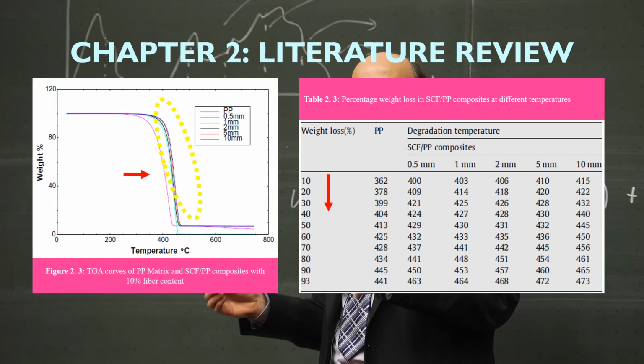Second, on additional observation, the degradation temperature and weight percentage loss of the composite sorted by different length, from 10% to 90% of the polymer, shifted the range from originally 362 degrees Celsius to 441 degrees Celsius, to 400 to 463 degrees for 0.5 millimeter length of short carbon fiber. This follows as the length increases from 1 millimeter to 2 millimeter to 5 millimeter to 10 millimeter of short carbon fiber.